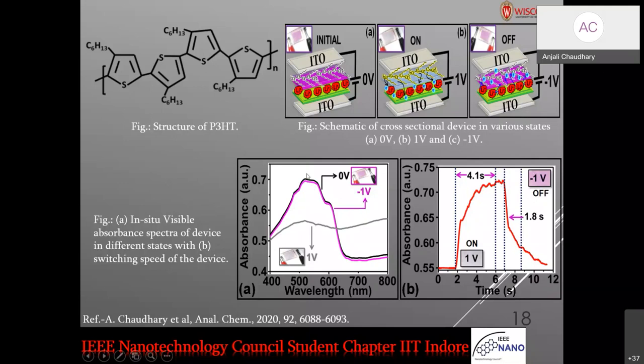And to see the optical absorbance difference at nearly 500 nanometer, and to see how much time it will take to switch between magenta and transparent color, we did the absorbance kinetics and found that it took nearly 4.1 seconds and 1.8 seconds to switch between the two optical states.